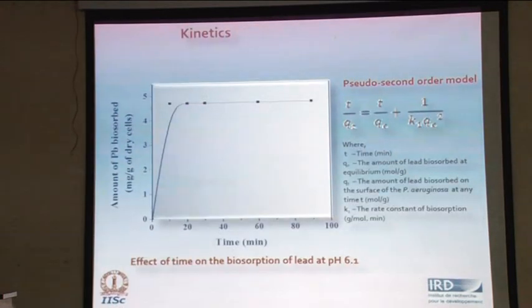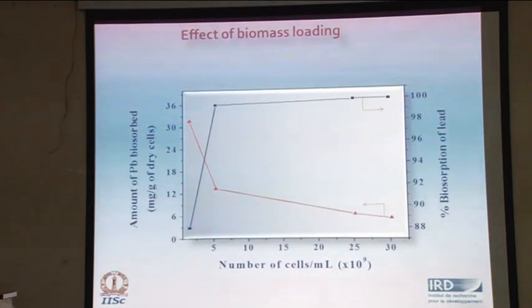If you see the kinetics, you can see that it follows the pseudo second order kinetics. Again, one can do these tests to establish basic parameters for scale up. If you look at the biomass loading, you can see that as you increase the biomass, you will be able to have better capture of the metals. This is to be expected, and almost complete removal of lead could be achieved.